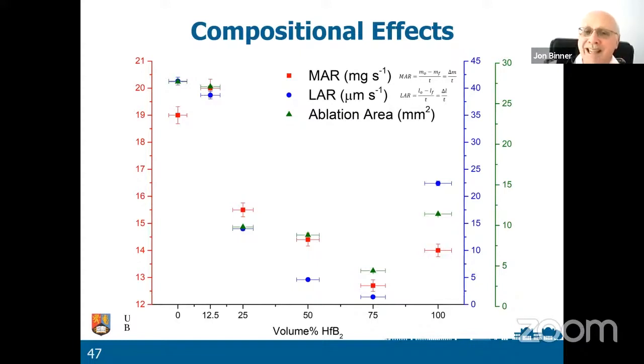So lower is better, and the ablation area smaller is better. You can see that if you have 100% zirconium diboride, you get quite a bit of damage. 100% hafnium diboride, you get less damage. But actually, 75% hafnium diboride, 25% zirconium diboride gives you the least damage of all.